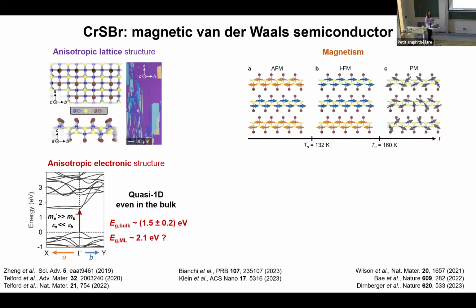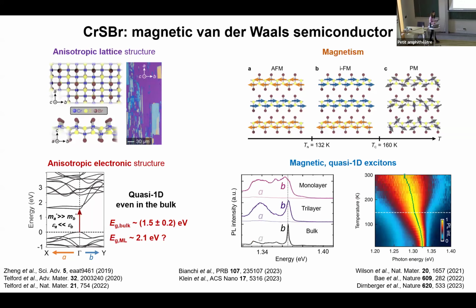Now, when we shine near-infrared light onto this anisotropic band structure, we end up having an equally anisotropic excitonic structure, as has already been observed by photoluminescence measurement. The photoluminescence measurement shows a highly polarized emission along the B axis, where the peak around 1.36 electron volts is the 1s exciton recombination peak to the ground state. However, when we study the emission properties along the A direction, we see a highly suppressed response.